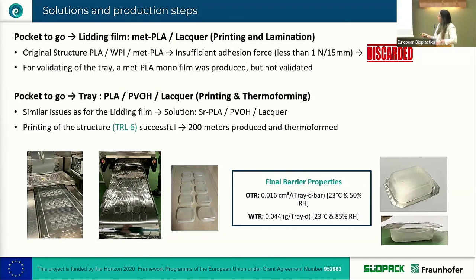The same problem was faced for the tray. We saw that the lamination wasn't possible because the adhesion between layers with PLA wasn't successful. And now, if we want to make a change, we have to think in another way. And that's why we decided to go for another solution. This self-reinforced PLA had actually very good mechanical properties, and we thought, what about to decrease the oxygen transmission rate just with a coating, PVOH in this case, and then we protect the coating with a lacquer.